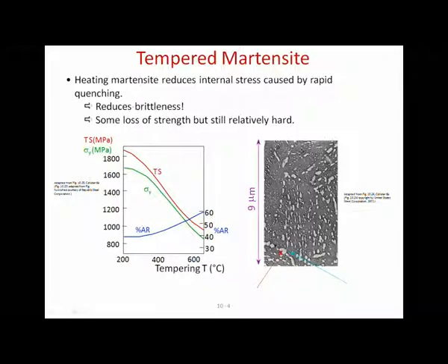And so this is an SEM image, a secondary electron image. You can see that those precipitates are on the order of tens to hundreds of nanometers. Okay, you can see these tiny, tiny ones there. So this is 9 microns. So that right there, maybe a little bit more than that. That is 1 micron or less, that little rectangle.